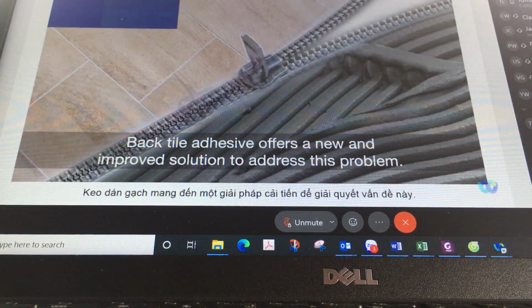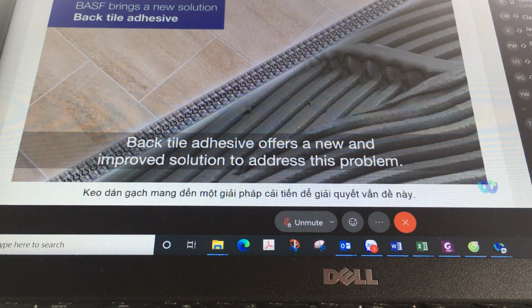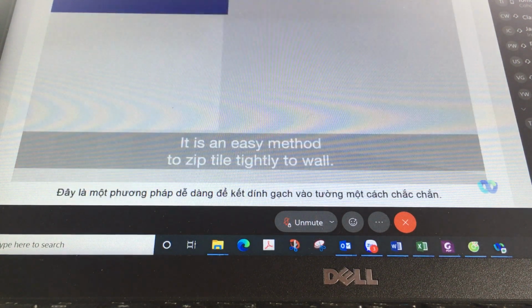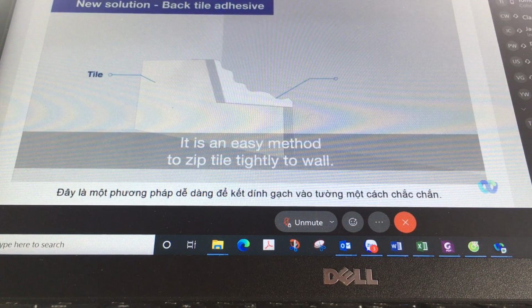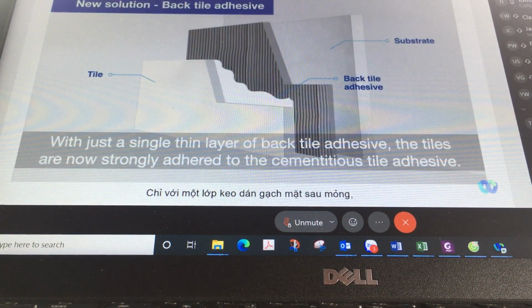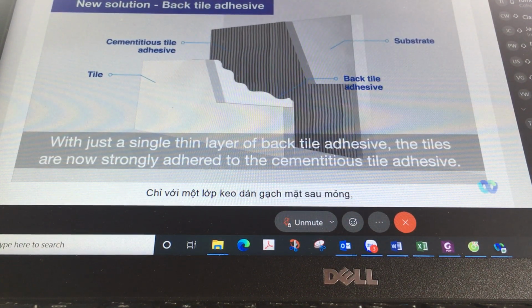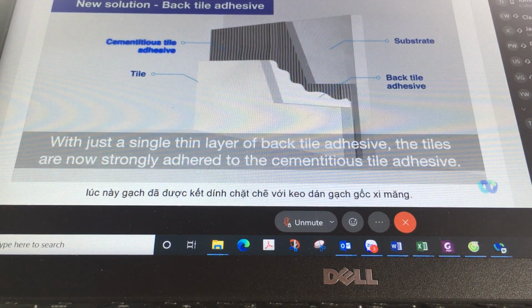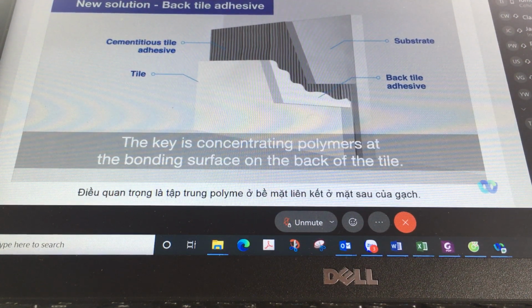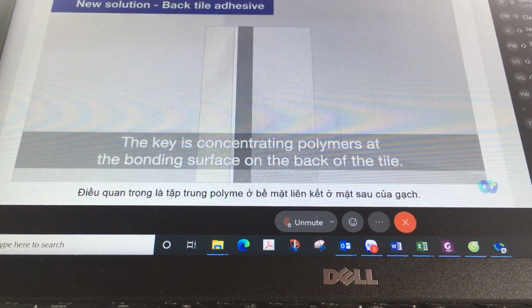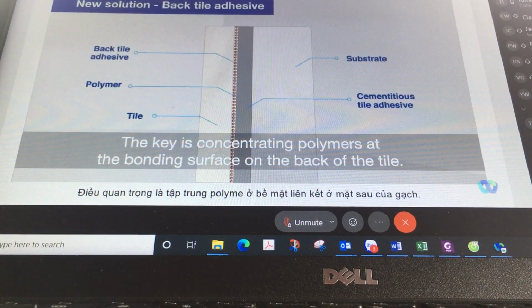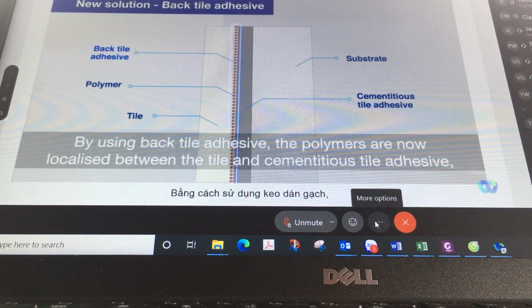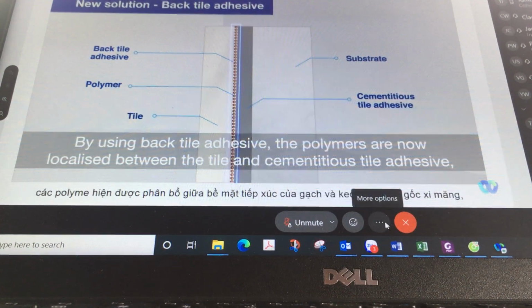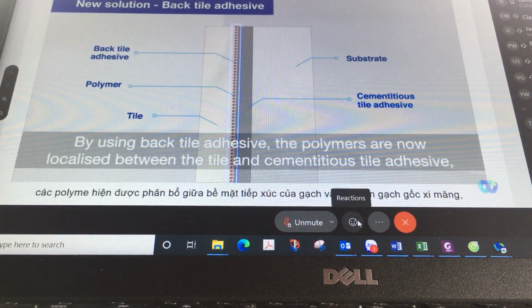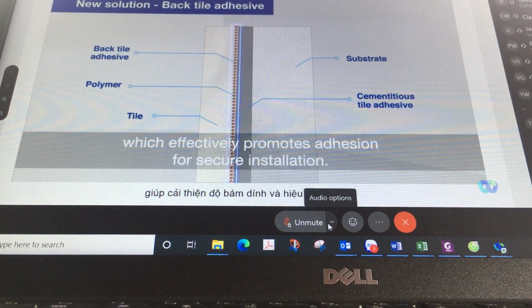Back tile adhesive offers a new and improved solution to address this problem. It is an easy method to zip tile tightly to wall. With just a single thin layer of back tile adhesive, the tiles are now strongly adhered to the cementitious tile adhesive. The key is concentrating polymers at the bonding surface on the back of the tile. By using back tile adhesive, the polymers are now localized between the tile and cementitious tile adhesive, which effectively promotes adhesion for secure installation.